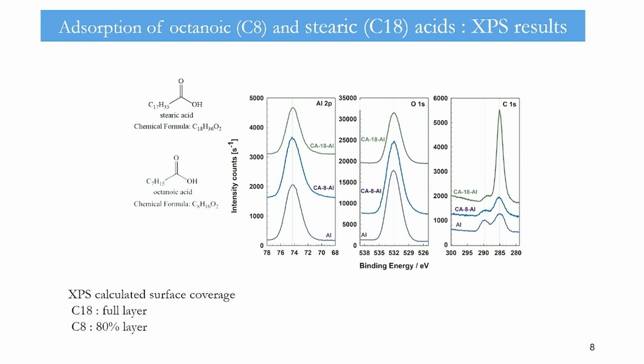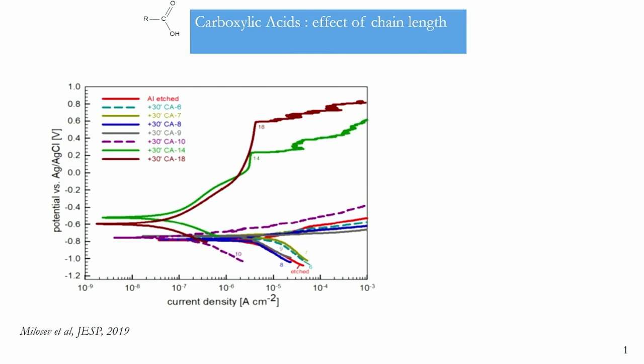Looking at the electrochemical curves for all carboxylic acids as a function of chain size, there is a threshold: you need molecules longer than about C14 to have a very good effect. For example, C10 has no effect. This could be linked to the fact that for C8 only 80% of the surface was covered, whereas for C18 the full surface was covered.